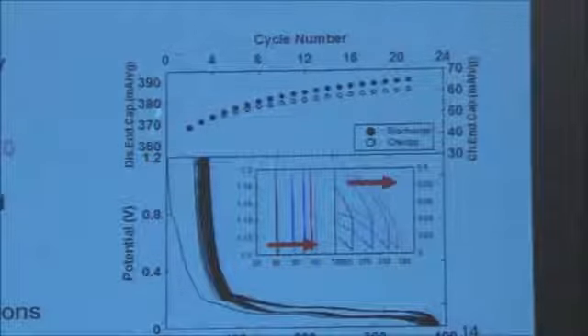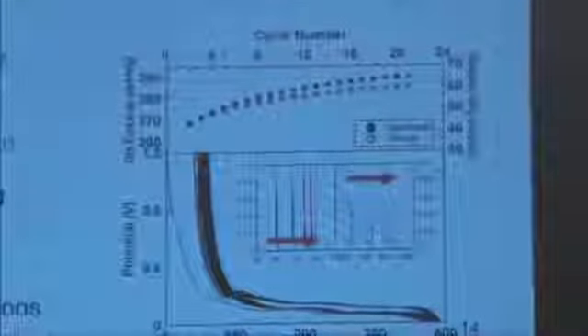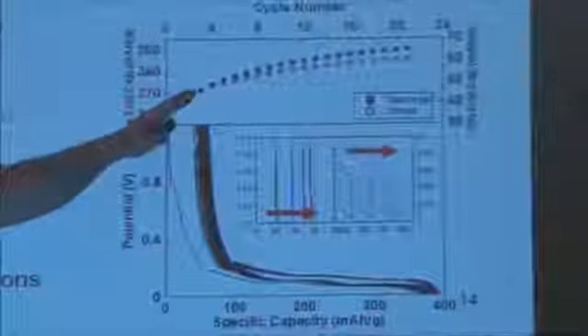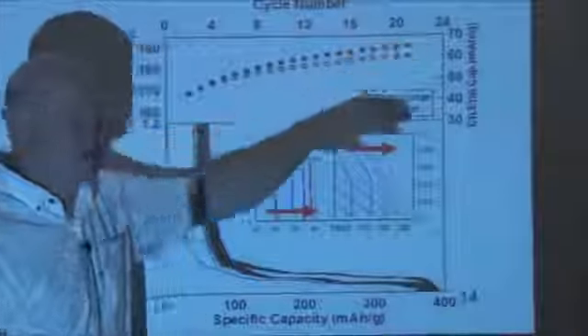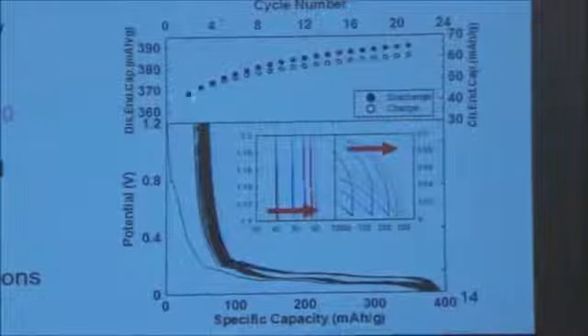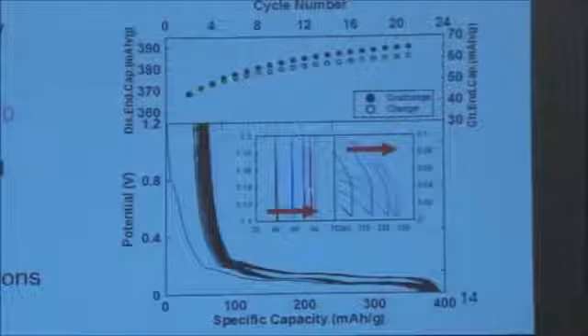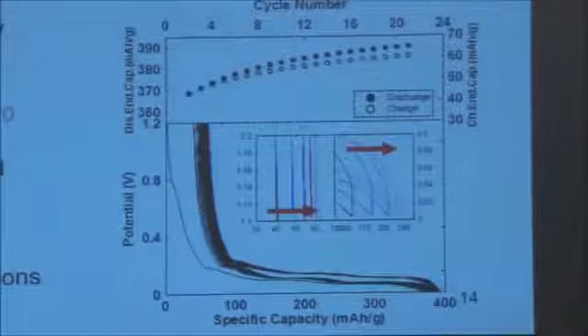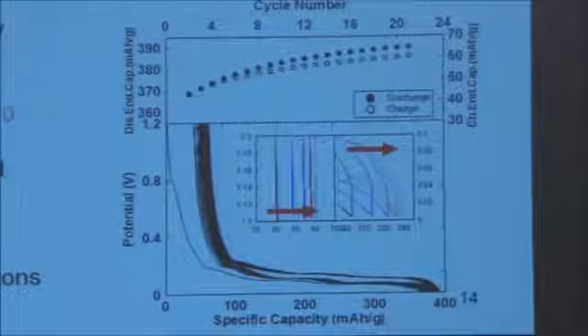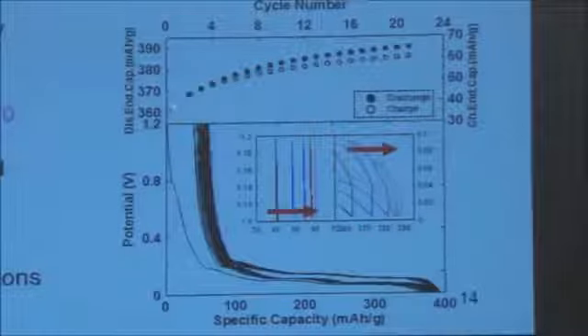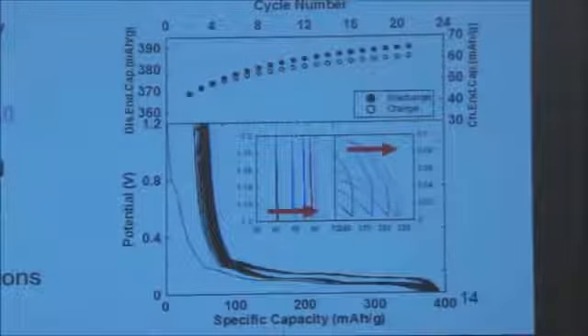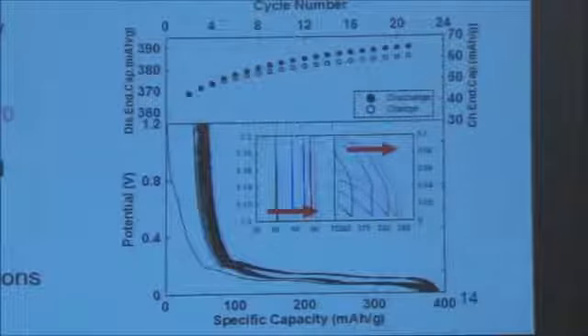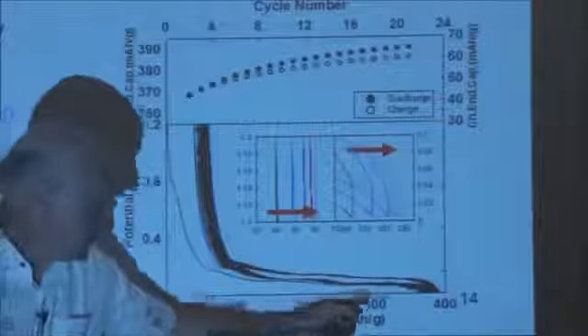In the top panel here, I'm plotting the discharge endpoint capacity, the point at the end of discharge, as a function of the cycle number in the black dots. You can see it increases rapidly and then starts to slow down. And the top of charge has exactly the same behavior. It moves rapidly at the beginning and then starts to slow down as the film thickens and becomes more protective. We call this motion charge and discharge endpoint capacity slippage. Call it slippage because this is slipping to the right. I'll talk about slippage from time to time.